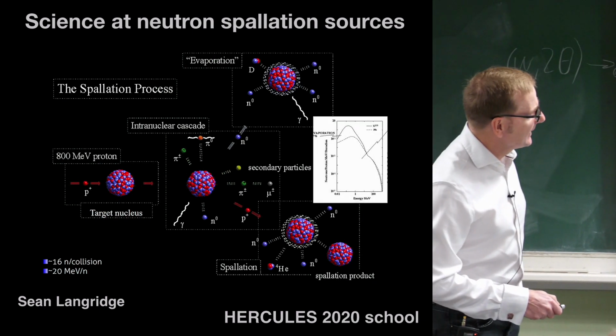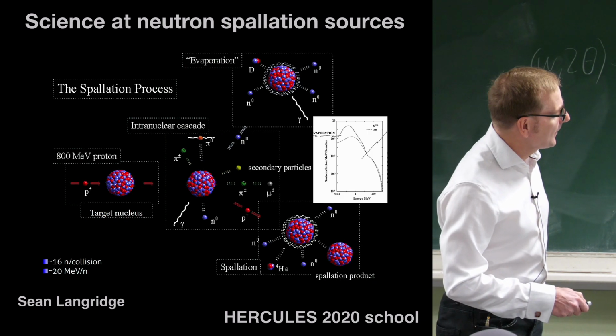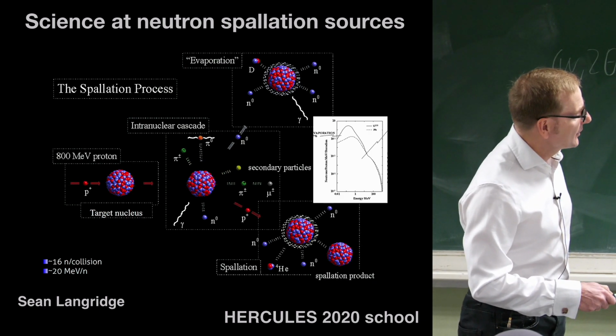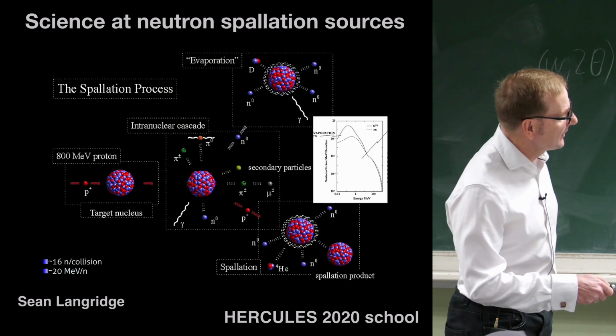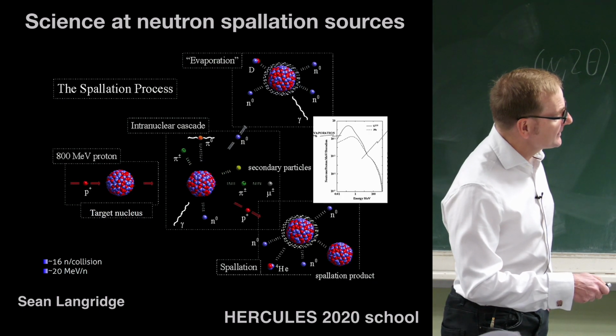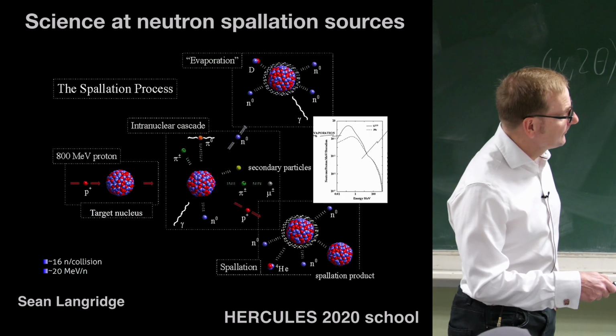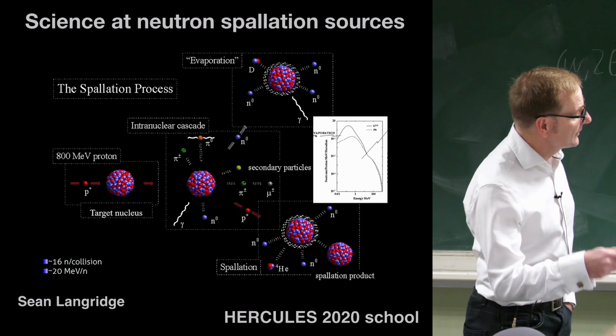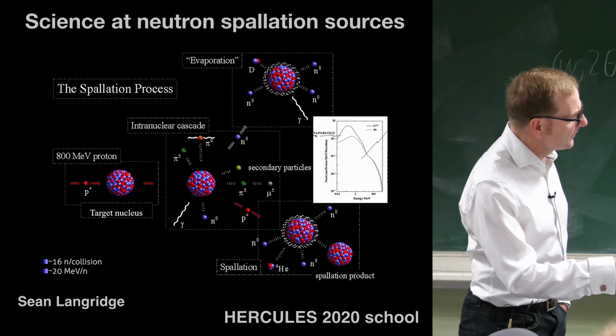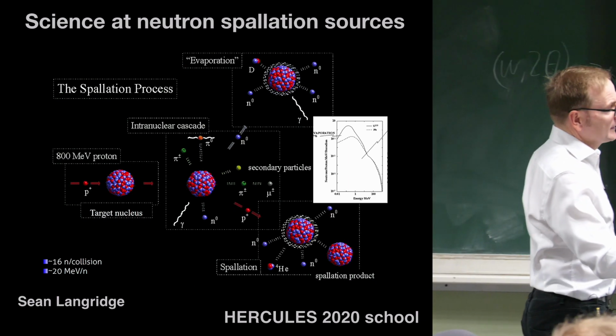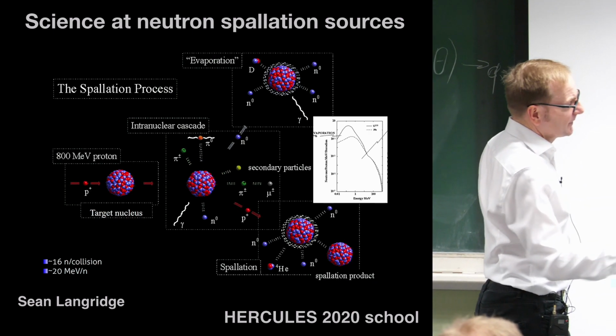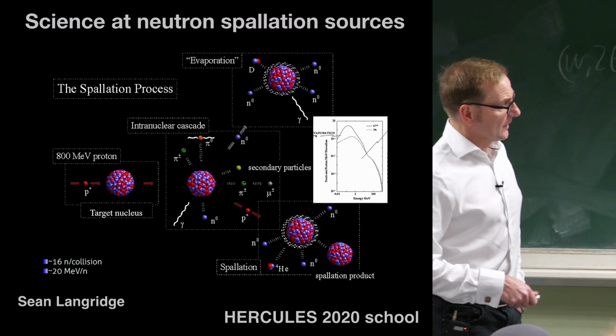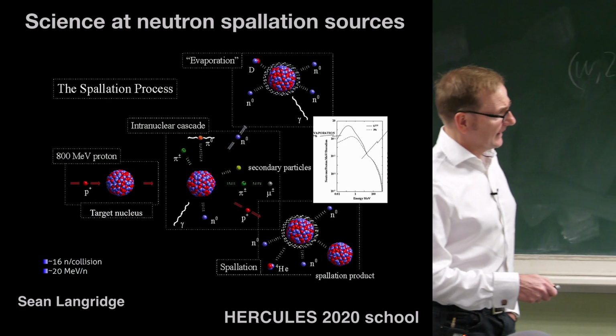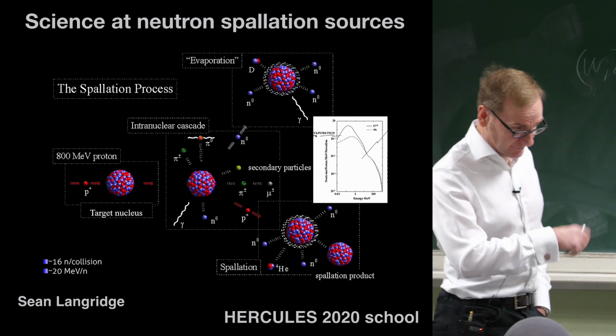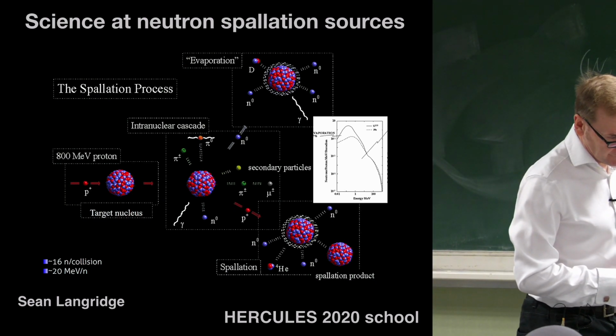Okay? So here's the energy. This is just some old data. I can't remember where it was taken from. Number of neutrons for a range of different targets. So in this case, uranium and lead. So uranium is very nice. It gives you a large flux of neutrons, but it has some other problems, and there's delayed neutrons and so on. So we don't use uranium, even though it would give us the biggest flux of neutrons. So at my lab, we use tungsten clad in tantalum, and the ESS we use tungsten, as you shall see.